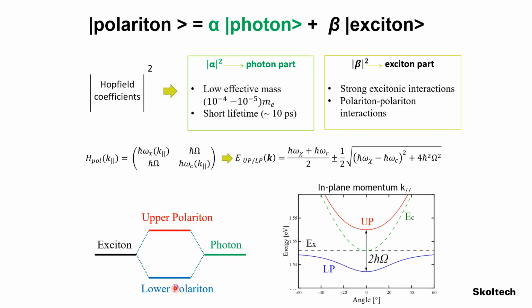If I look at the dispersion of the photon in the bare cavity with the green dashed line here, it is parabolic. That is because we have confined one direction. So I go from a conical to a parabolic bare photon dispersion. And therefore, now if I couple the photon with the exciton, which is also a parabola, but because it's much heavier, it appears to be completely flat for the range of angles that I can access experimentally.